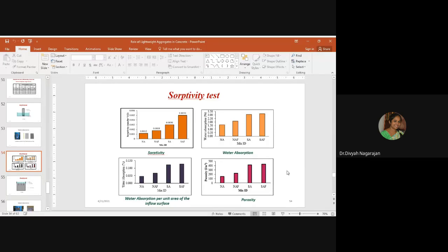Now, coming to the porosity, the presence of voids in concrete can be filled with or without water. It is known that the more porous the concrete, the weaker it will be. However, in the present mix proportion, it is proportioned in such a way that the strength was similar. The porosity of the lightweight concrete and fiber reinforced lightweight concrete was found to be more than the conventional.